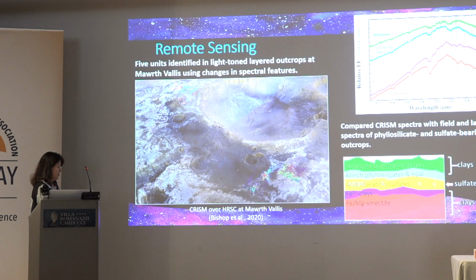And so looking at this particular spot in Mawrth Vallis, we look at these spectral shapes, and we have a water band here, and then we have OH bands here, and these change depending on the cations and octahedral sites. And so there's a lot of this iron magnesium smectite. Sometimes there's some ferrous clays and some acid alteration or sulfates, and then we see aluminum-rich phyllosilicates and then some nanophase materials at the top.